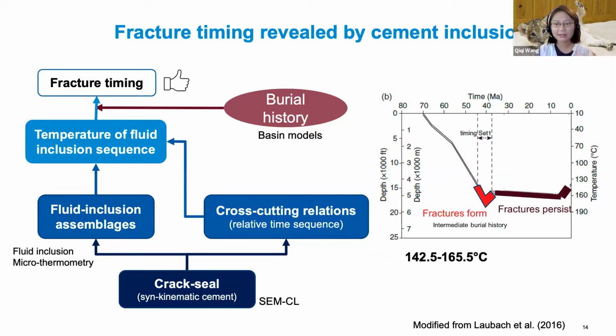So if we map that time and temperature sequence to the burial history curve of our intermediate core, with measured in situ fluid temperature being around 142.5 to 165.5 degrees C, then we can locate when our fracture was formed in the burial history. So in our intermediate core example here, I show the studied fracture was active around 45 million years ago and stayed active for around a few million years. Then after that, it retained open pore space within the fracture for around another 38 million years. Obviously, there's uncertainty associated with this type of analysis, I want to emphasize, and it really requires a good basin model and really good fluid inclusion measurements to make this method valid.